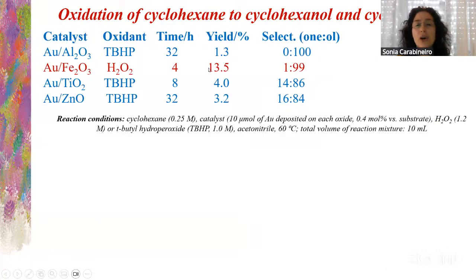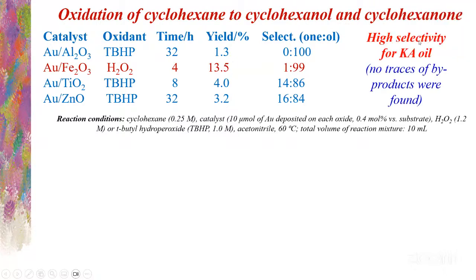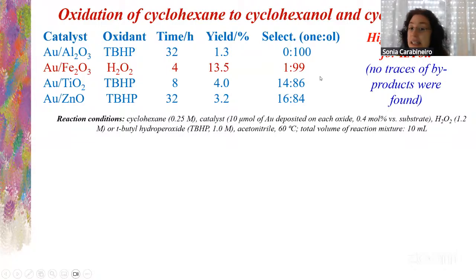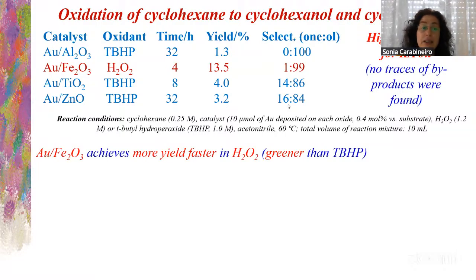So we could obtain a much higher yield with gold on iron oxide, using a very environmentally friendly green oxidant, H2O2. So we obtain a value higher than the commercial one, and high activity. The selectivity is very high, above 99%, because no traces of byproducts were found. And the industrial process has selectivity of only around 80 to 85%. So this is quite good. And of course, this one is faster, in 4 hours. The other one needed more time. And this one is a greener one.